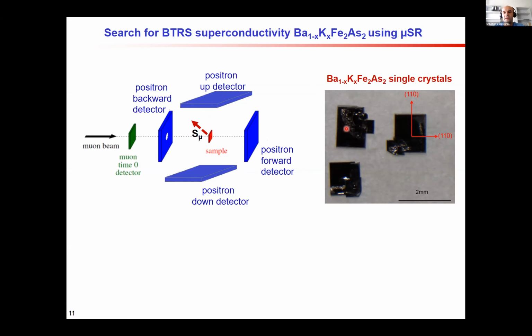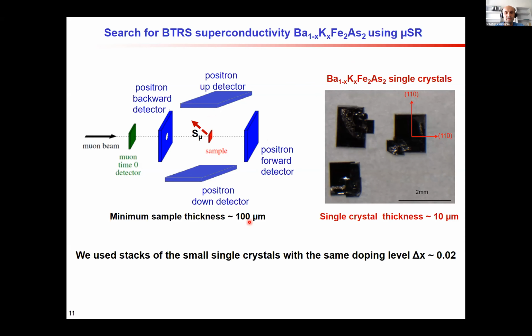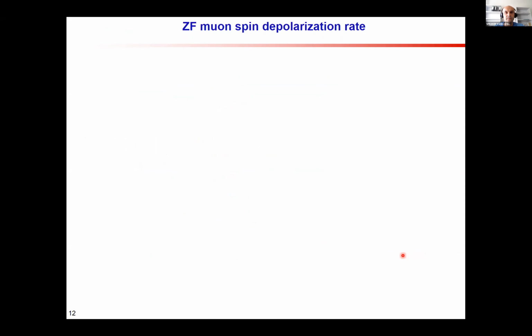And the main complication for our study is that samples of barium iron 2 arsenic 2 are very tiny, very thin single crystals. So the average thickness of these crystals is about 10 microns, at the doping of interest. However, for the experiments, we need about 100 microns. And so it means that we need to stack a lot of crystals together, and every crystal must be checked, so that the doping varies between crystals only within 2%.